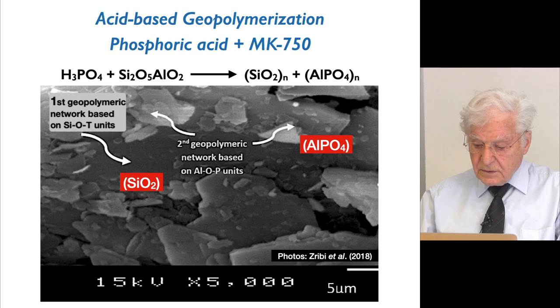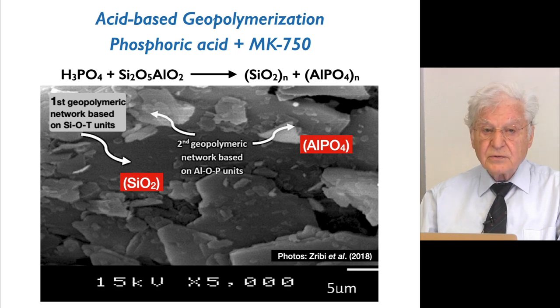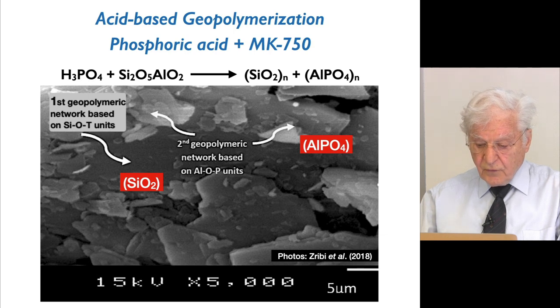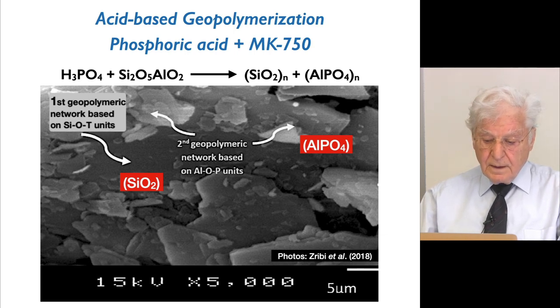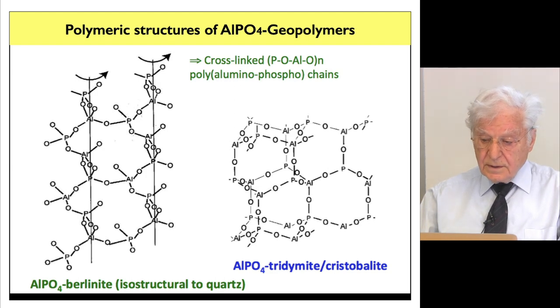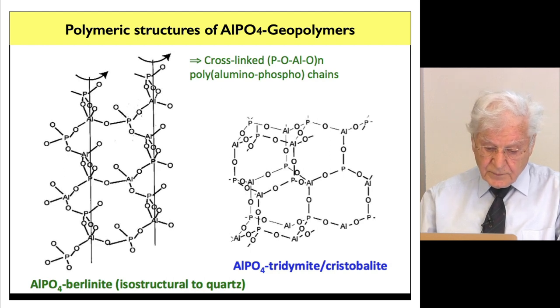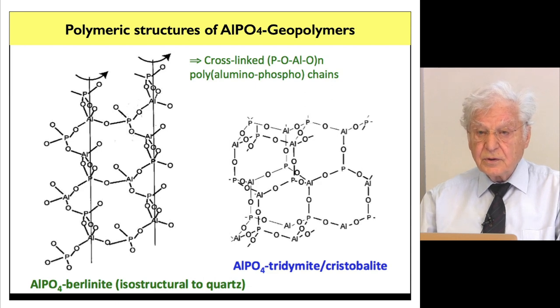The problem is that we see the solid solution of these two polymeric networks, SiO2 and AlPO4, aluminum phosphate, only under the electron microscope. Why? Because the X-ray diagrams of the aluminum phosphate geopolymer are identical to the X-ray diagrams of SiO2. This is the first step, which is called berlinite, aluminum phosphate berlinite, with its helicoidal structure. And it is exactly similar, identical in structure to the one of quartz. We say it is isostructural to quartz.